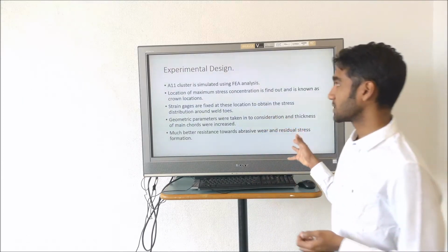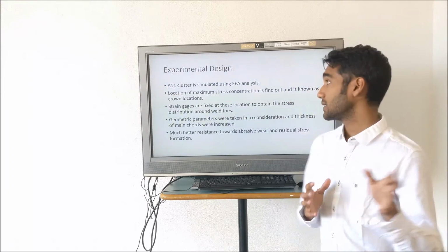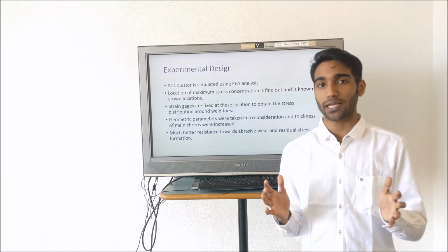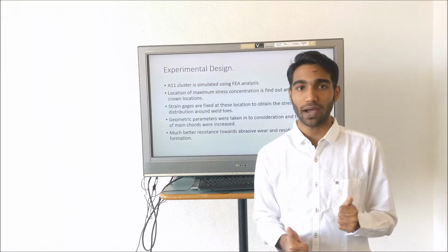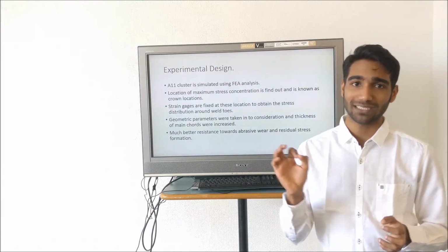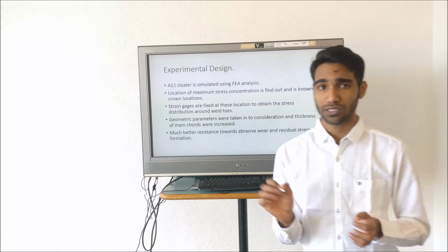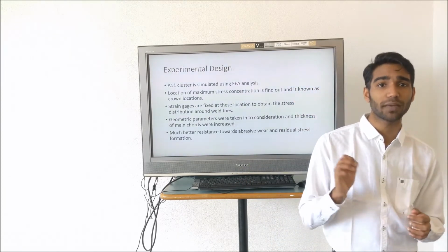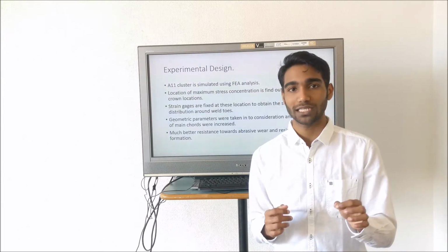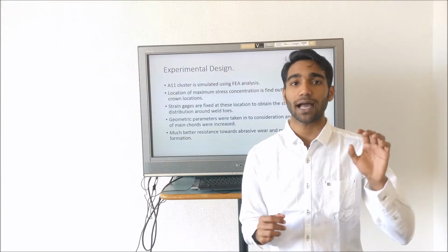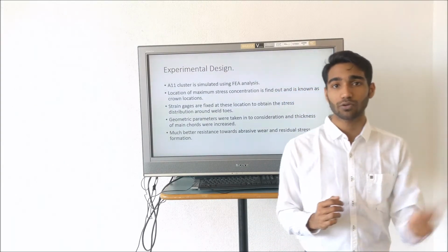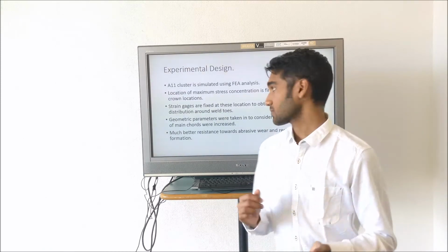Now the experimental design. First of all, the virtual simulation of the A11 cluster, which forms at the dragline boom, is done using finite element analysis. The next step is to locate the point of maximum stress concentration, and these points are known as crown locations. For this purpose, we make use of finite element analysis. Once these points are located, mechanical strain gauges are installed at these locations so that stress distributions around the weld toes are obtained.